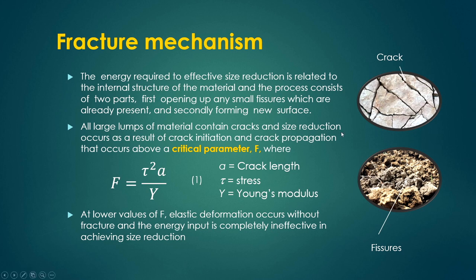Okay. So, this crack initiation and crack propagation will occur above a certain critical parameter that is represented by F, and that F can be defined by tau squared A by Y. Here it is shown in the slide, that equation: F is equal to tau squared A by Y. What is that? Tau is basically the applied stress on that particle, A is the crack length as shown in the picture, and Y is the Young's modulus.